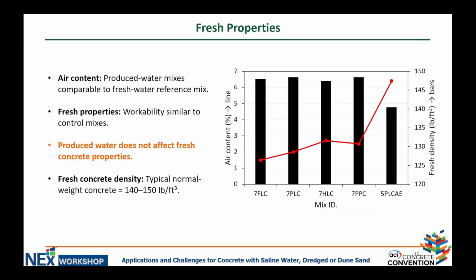That is the message. Then we can see here basically the air content, which is the red line on the left axis, and the fresh density. Again, fresh density was not affected at all by produced water. The last mix basically has a slightly lower fresh density and higher air content. That makes sense because we added air-entraining admixture, so that's expected. But as we can see, air content also is slightly higher in the case of produced water mixes. But again, what we can see from this slide, produced water is not really affecting the fresh properties badly.